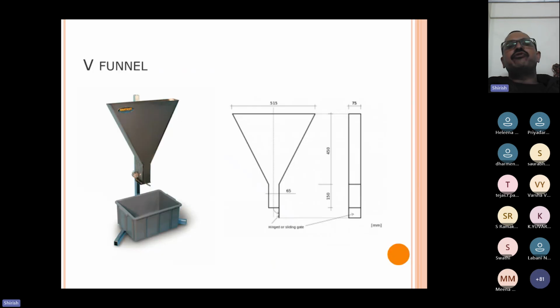This is the V funnel. We have to fill it with the self-compacting concrete and then open the gate at the bottom. When we open the gate, the concrete will flow down. But here, as you can see, the neck is made very narrow. The coarse aggregates, which have a tendency to settle down, will settle and block the neck of this V funnel. So if the segregating tendency is there in the concrete, it will block the neck, and because of that, the concrete will not flow through this narrow opening. This is what segregation is. If such a thing is happening, we will call the concrete segregating concrete. Then we may have to reduce the quantity of fine aggregate, or we may have to increase the quantity of paste.